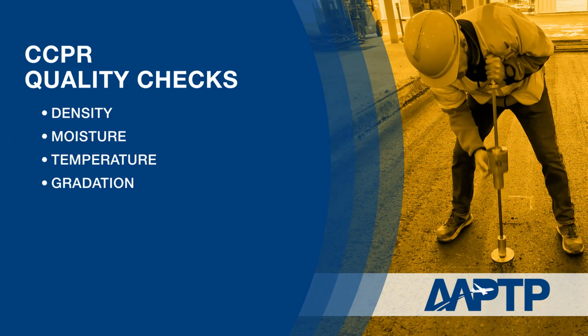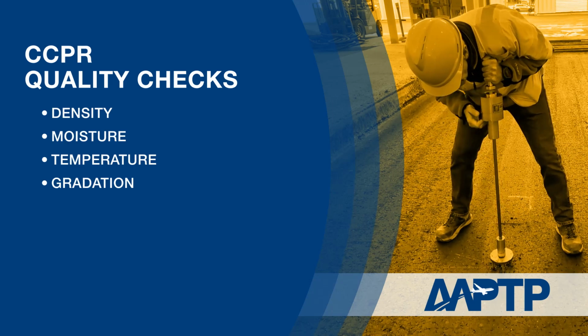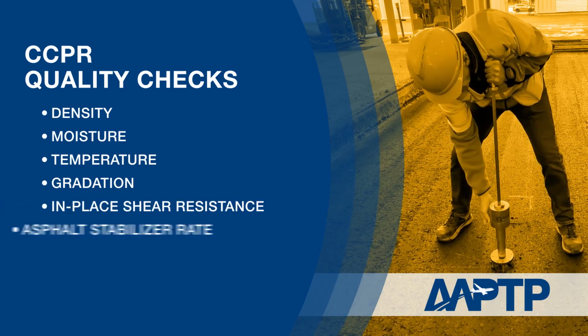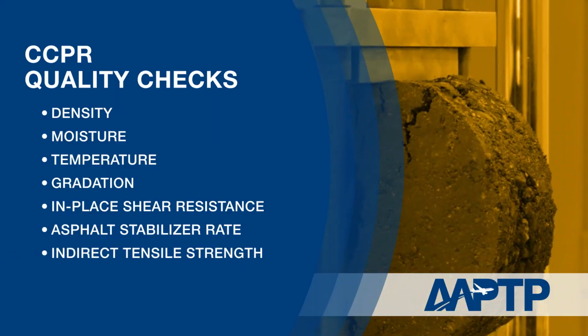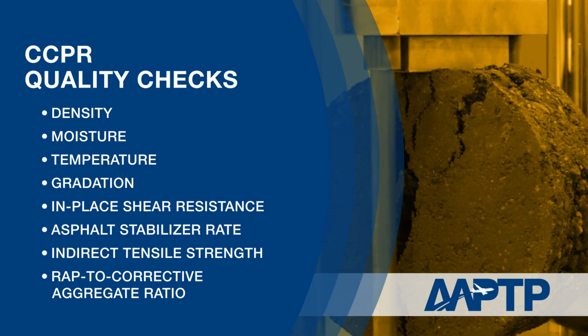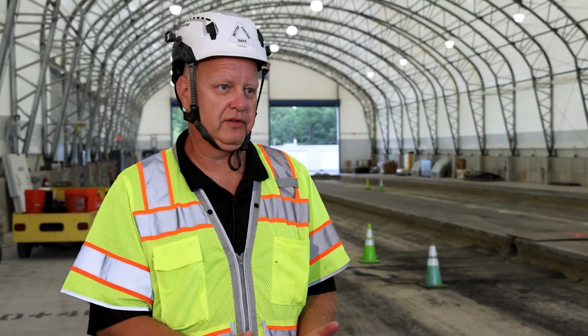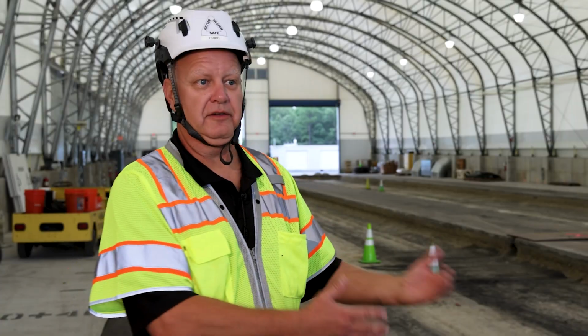Other quality control tests for CCPR include in-place shear resistance, asphalt stabilizer rate, indirect tensile strength, and the RAP to corrective aggregate ratio. CCPR also has a curing factor. You can't do that with hot mix; you can make it that day, test it, and have results by that evening. CCPR could take up to 72 hours, if not 96 hours, to get results. So when you do trial sections, they typically are done weeks in advance.